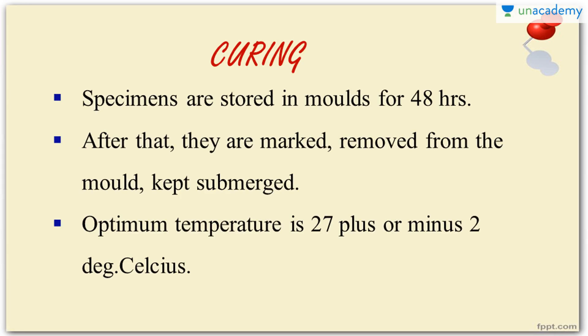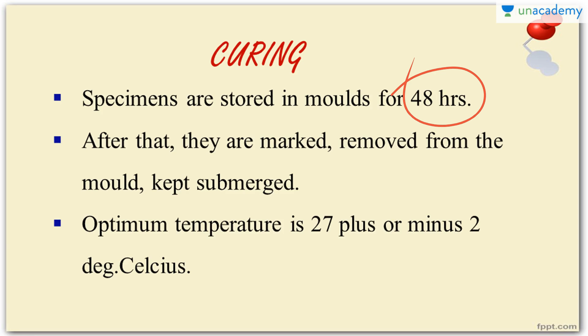After filling, the specimens are stored in the molds for 48 hours — note that the code specifies 48 hours, not 24 hours for this experiment. After that, they are marked according to the test days, carefully removed from the molds, and submerged in a water bath. The optimal water temperature should be 27 ± 2 degrees Celsius. The water must be checked every 7 days for any growth or unwanted external disturbance.